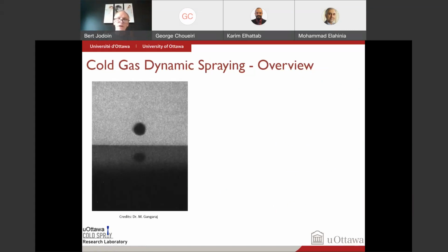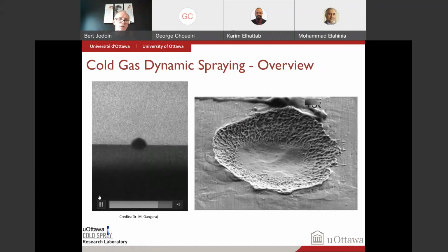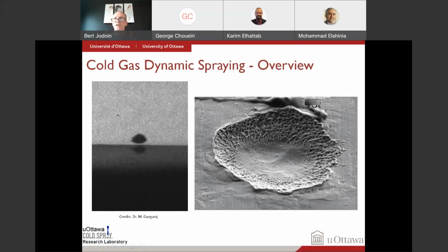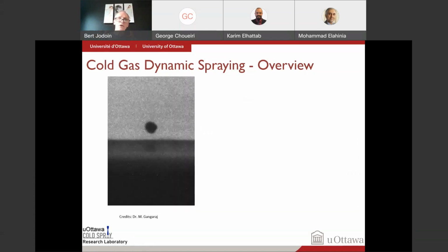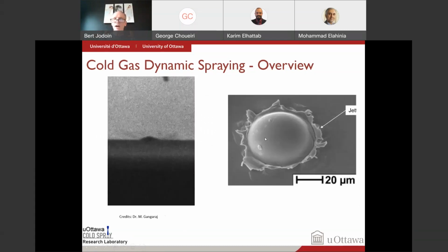So if we look a bit more carefully at what we get on the substrate after deformation, if we look at this surface on the microscope, this is what you're going to get. You get a crater there. Now, if we throw this little particle a bit faster, you see that it deforms and it stays there, it sticks. So we get this here, where the bottom deforms to such an extent that you actually get jetting of material. So our tiny particle deforms plastically and then sticks to the substrate. This is basically the fundamental of the cold gas dynamic spray process.